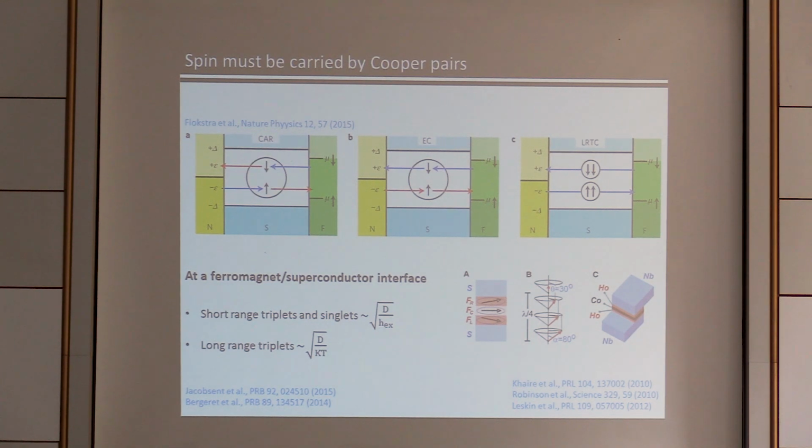And this, combined with the Rashba break of symmetry at the interface, is sufficient to open long-range spin channels in the niobium, through which spin pumped from the permalloy can propagate. Now, at the same time, as spin arrives into the platinum, it increases the spin splitting in platinum and acts as a positive feedback that makes this effect even larger.